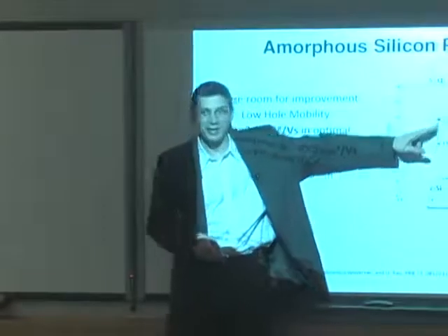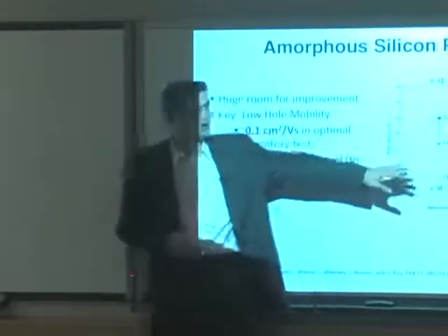Now, what's going on? Well, the key limiting factor in amorphous silicon is the mobility of the holes. Okay? It's thousands of times slower than in crystalline silicon. So the question we can ask computationally is, what's happening here? What's trapping holes? Okay? So let me show you how we're tackling this.